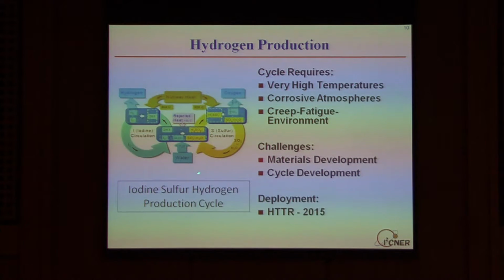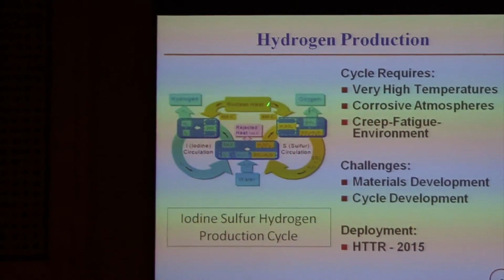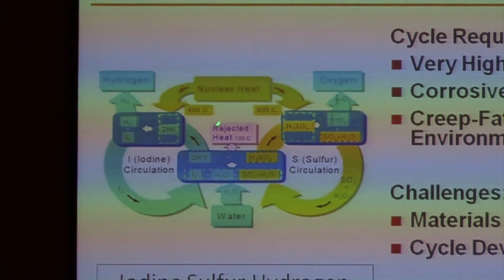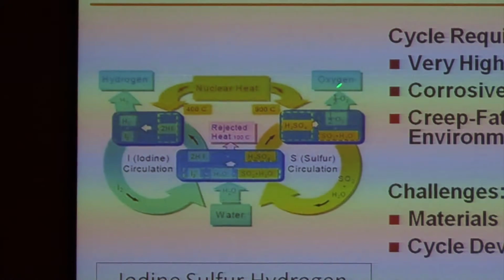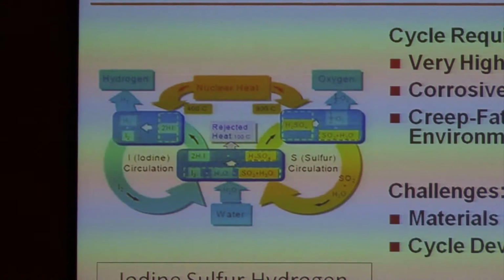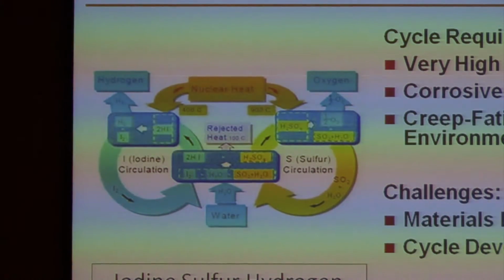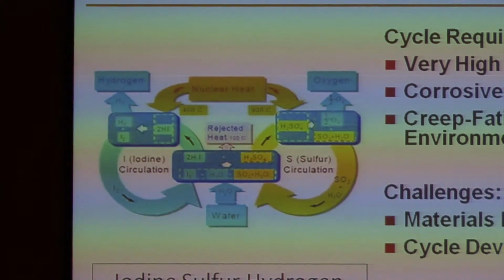And so this is the proposed, there are many cycles for producing hydrogen. This is the so-called iodine sulfur cycle, which is the one that's being pursued both in the US and here. High temperature nuclear heat up to 900 C, and a low end at 400 or 500 C, maybe even lower than this. And there are two cycles which produce hydrogen at the low end and oxygen at the high end. Okay? And this would be an efficient way. The calculations at least of the efficiency of the system, for hydrogen production, could exceed 50 or 60%. So thermal energy to hydrogen production.